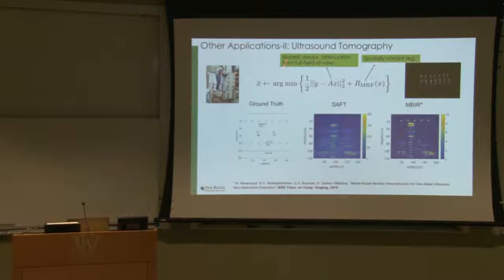At Oak Ridge, a few folks created a test structure with a bunch of known defects, and they processed the data using a standard technique, which is very fast, and using these model-based techniques, which is not as fast, but pretty close. But we can start seeing defects a lot more clearly with these model-based techniques. And again, you can refer to the paper. I just want to give you a flavor of what was done.